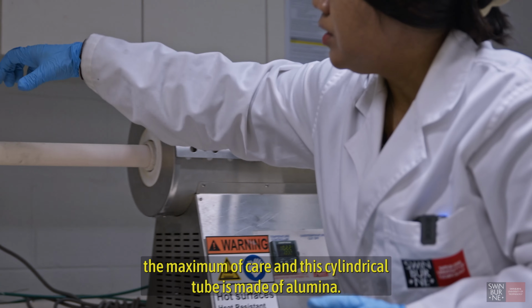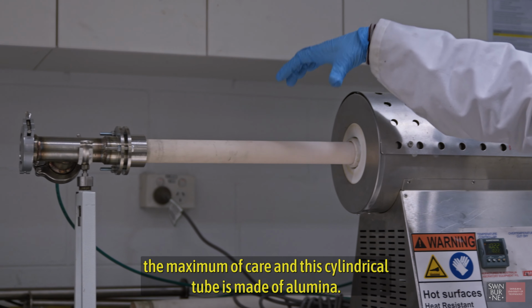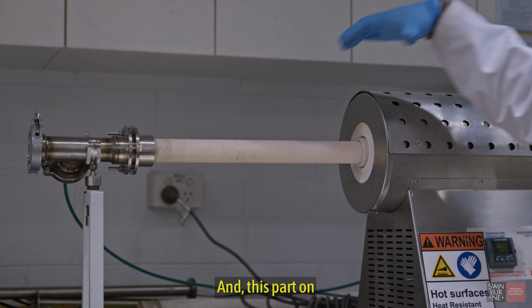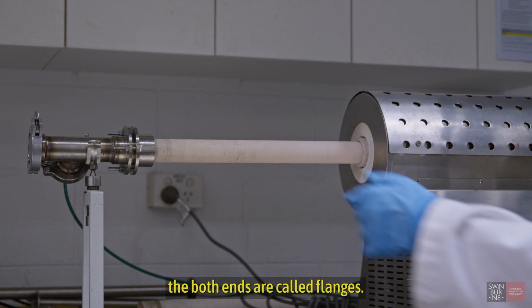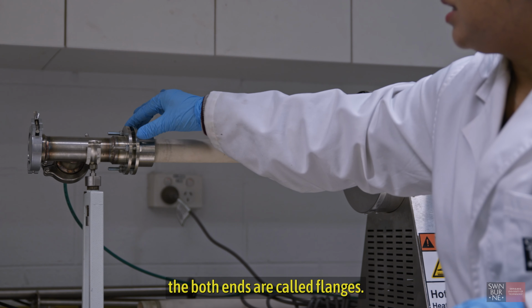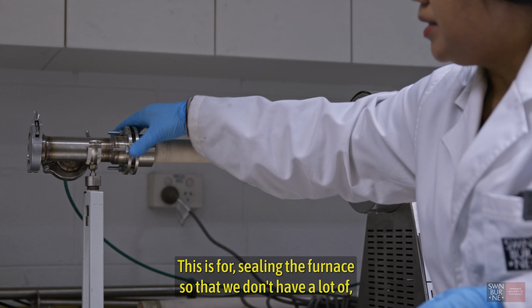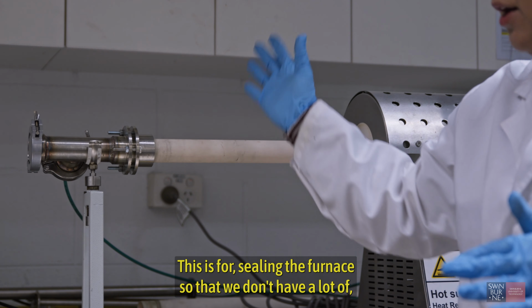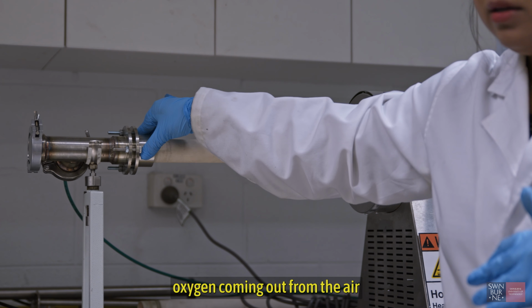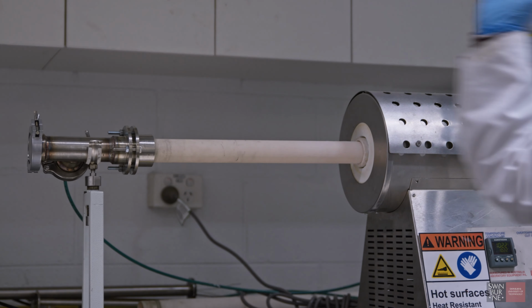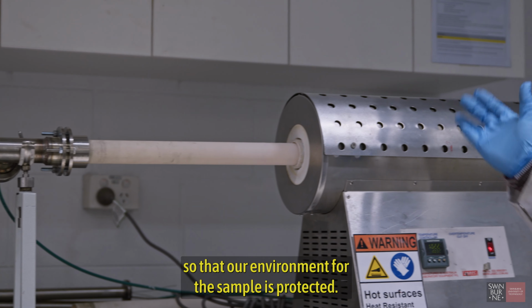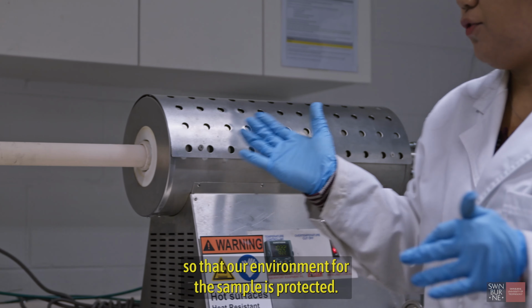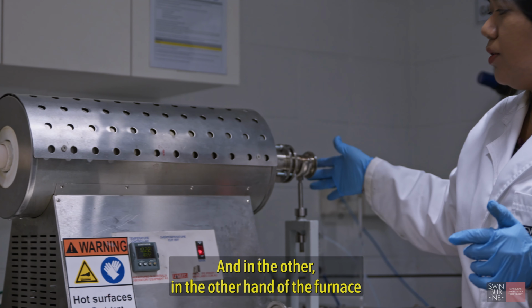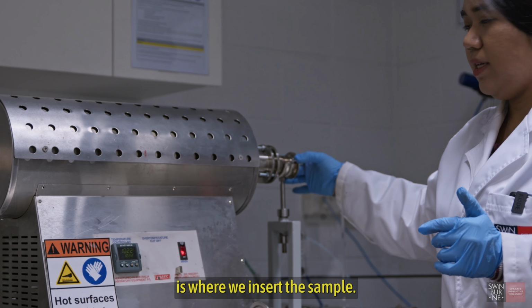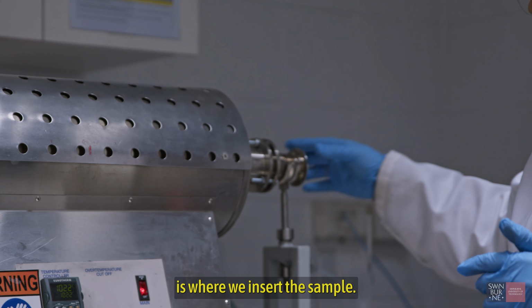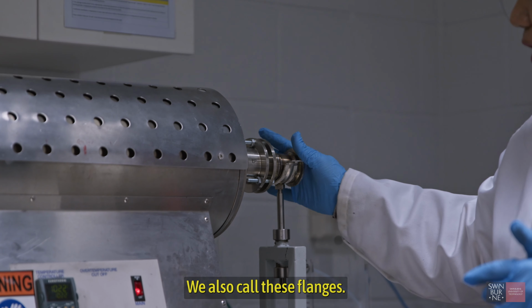And this cylindrical tube is made of alumina, and the parts on both ends are called flanges. This is for sealing the furnace so that we don't have a lot of oxygen coming in from the air, so that our environment for the sample is protected. And on the other end of the furnace is where we insert the sample. We also call these flanges.